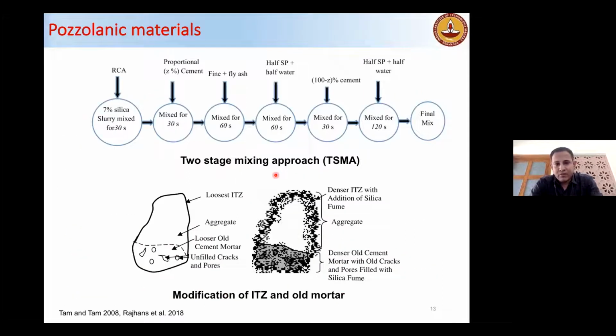Coming on to the next type of treatment where the modification of surface is done. So it could be done using the pozzolanic materials. So you can use silica fume and fly ash or cement. So basically this is the process where first you try to coat the aggregate with the pozzolanic material, and then after several stages of mixing and adding the different constituents at different times, you get the concrete. So with this concrete, what happens is the ITZs are densified. Also, this attached mortar, which is porous and there could be some cracks.